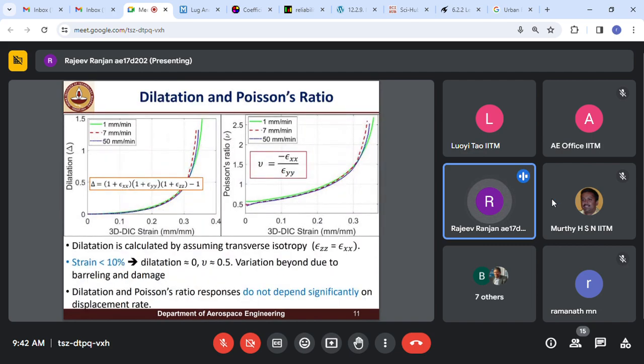During compression loading, dilatation and Poisson ratio were also determined. The same finite strain dilatation formula and formula for Poisson ratio which were used for tensile loading are used for compression loading also. And we observed that up to around 10% of the strain, dilatation was nearly zero, and the corresponding Poisson ratio was close to 0.5. However, after that, both dilatation as well as the Poisson ratio were increasing, and it seems that the reason behind this is the barreling and damage in the material.